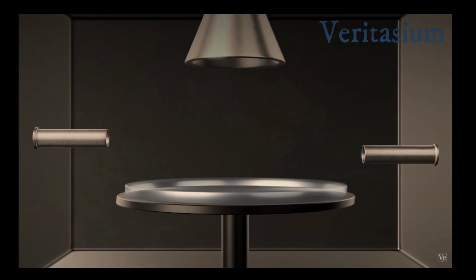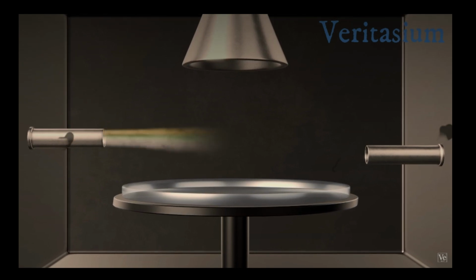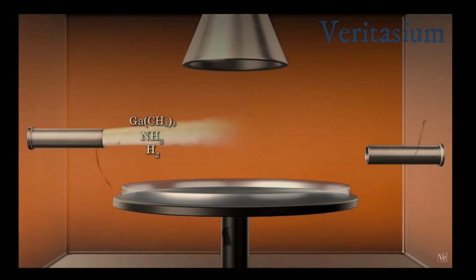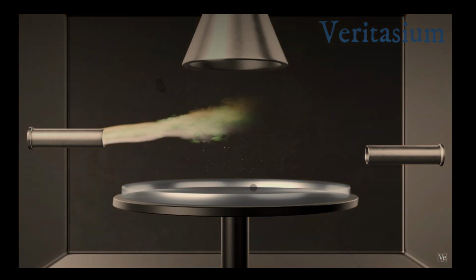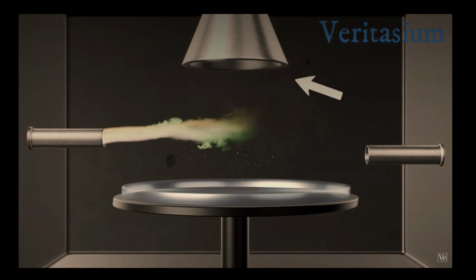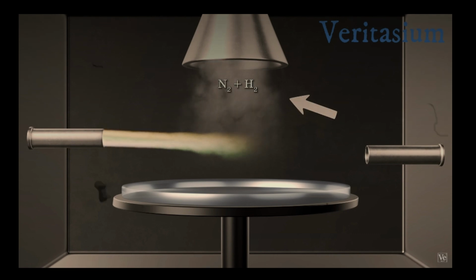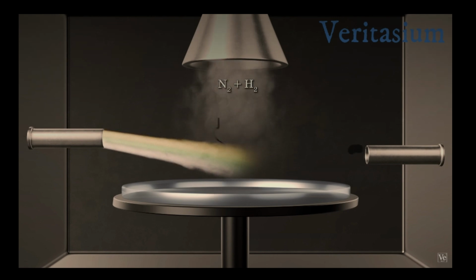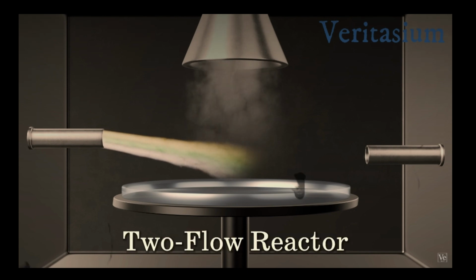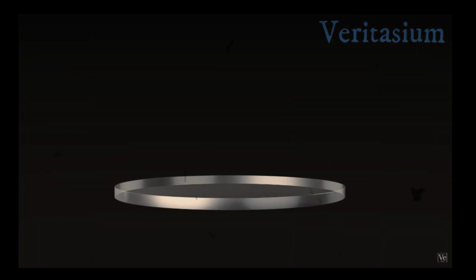His trick was to add a second nozzle to the MOCVD reactor. The gallium nitride reactant gases had been rising in the hot chamber, mixing in the air to form a powdery waste. The second nozzle released a downward stream of inert gas, pinning the first flow to the substrate, to form a uniform crystal. For years, scientists had avoided adding a second stream to MOCVD because they thought it would only introduce more turbulence. But Nakamura used a special nozzle so that even when the streams combined, they remained laminar. He called his invention the two-flow reactor.